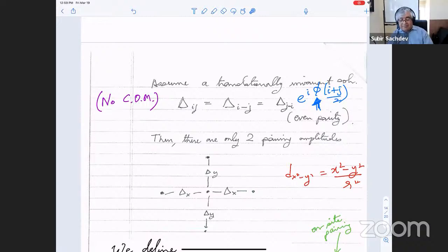Yeah. So in the previous chapter, when we talked about helicity modulus and all of that, the phase in the helicity modulus that I was twisting was this one. It wasn't the one that depends on the relative coordinate. That's rigid. So in a D-wave superconductor, it has opposite signs. To measure the difference between delta x and delta y, you have to do a very clever experiment where you tunnel in only in the x direction and only in the y direction, and you do some interference between them, which is the experiment done by Kirtley et al., which established very clearly that this was a D-wave superconductor.